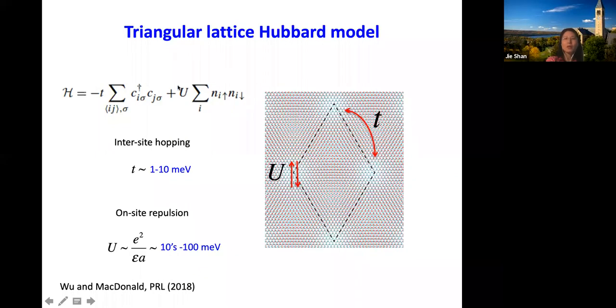One is this U, which is the on-site repulsion energy. So how much energy you need to pay to put 2 electrons at the same site. Here, this length scale is not the period, it's the size of the electron wave function. You can think about that. And this U is on the order of 10 to 100 meV.